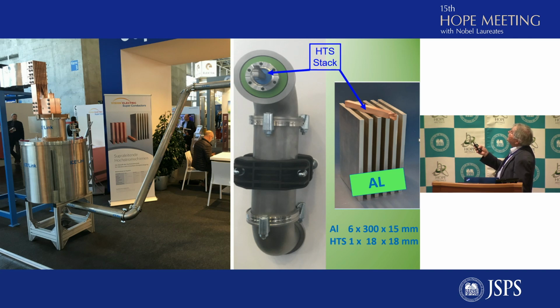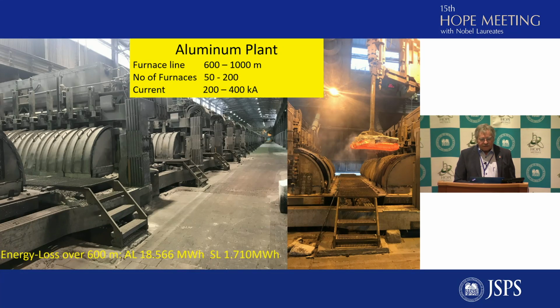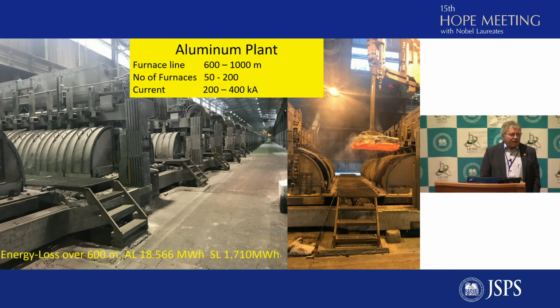And this part is a superconducting stack. Here you have again the comparison between the aluminum bars and the superconductor being able to carry the same amount of current. So what's planned at the beginning in the next year is the installation of a 200 kiloamp bus bar based on superconductors in such an aluminum plant, which is a furnace line which can be 1 kilometer in length, up to several hundred furnaces to melt aluminum in a row. The current which is needed is 200 to 400 kiloamps, and you will find the superconducting counterpart to this row of current line on the backside of the installation.